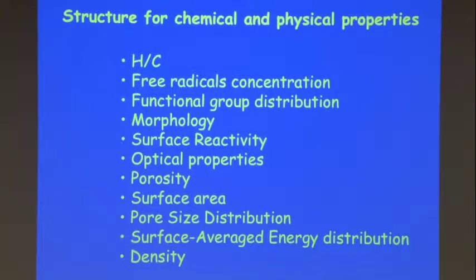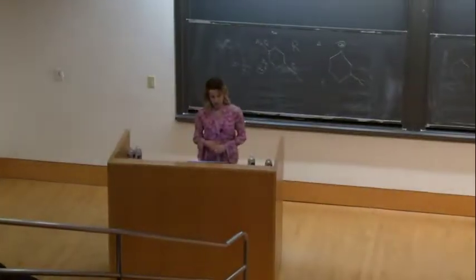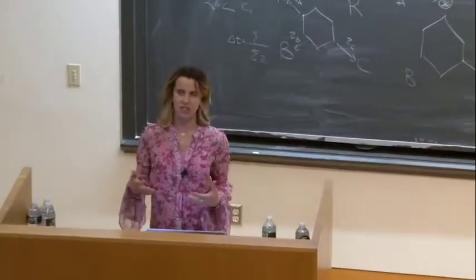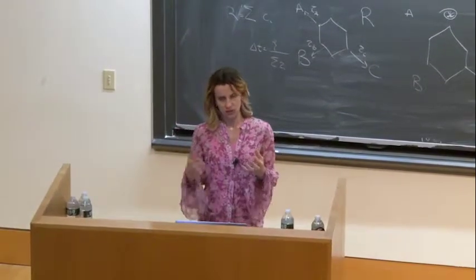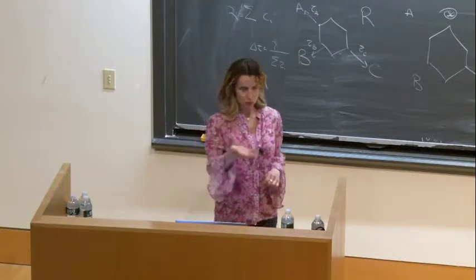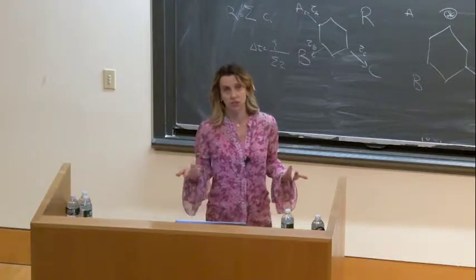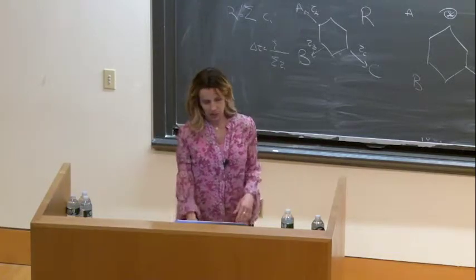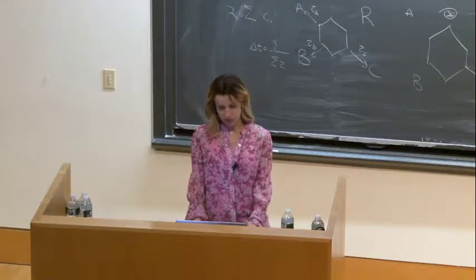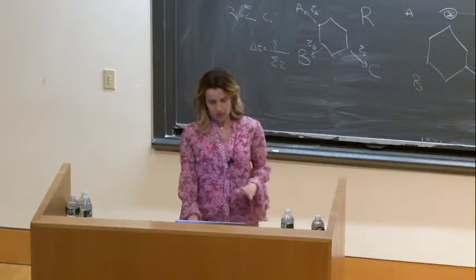So optical properties: once you have a structure, you can compute the spectrum, and so you can see the absorption spectra of those nanoparticles. You know that those emissions have an influence on the atmosphere, on the environment, on incoming radiation, and so the structures influence this interaction. So having the XYZ of this nanostructure, then you can compute maybe with DFT, time-dependent DFT, some spectrum. Porosity, surface area, and density of those particles are also interesting. So anyway, this is modeling.